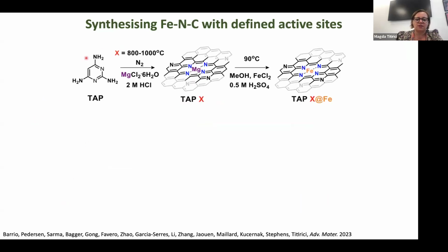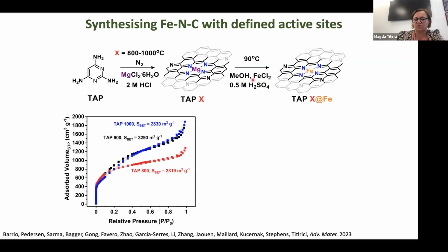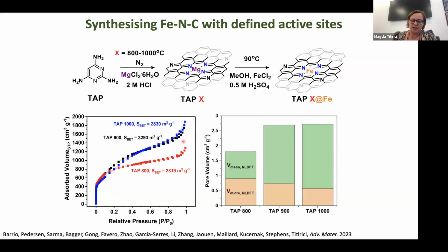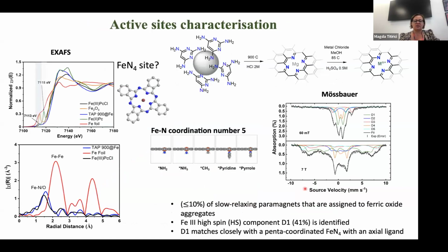So as I said, you start with this triaminopyrimidine. You work in the presence of magnesium chloride hexahydrate. You form this porous framework, which has this nitrogen magnesium configuration. And then you come at a low temperature and you exchange this magnesium for your metal of choice. You could do iron, nickel, chromium, cobalt, whatever you want. The advantage of this method is that it gives you a very high surface area material because you are templating it in situ with this magnesium oxide. And you would see that at 900 and 1000 degrees, this material contains mostly mesopores. And why is this so?